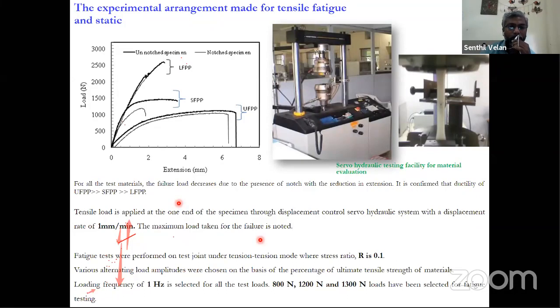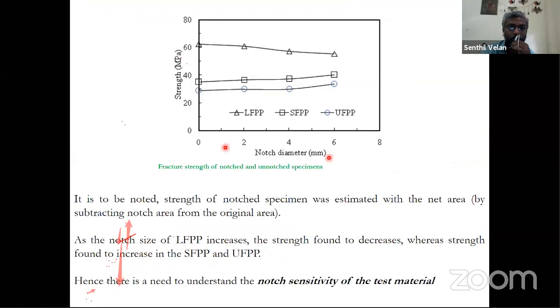You will be able to see that the fracture strength, if you look into this, under this class of material, which is a long fiber one, shows a drop. Whereas both the unreinforced and the short fiber materials, here we have used a different class of material. It's polypropylene. In the earlier studies, we used polyamide, which is a nylon-based material. So here you can see that when the notch diameter is increased from 2 to 4 to 6, there is an increase.